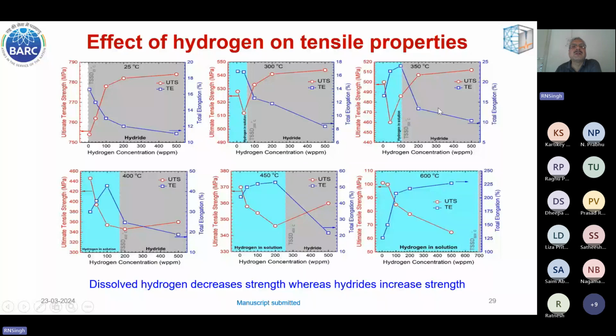You can see that when hydrogen is present in solution, the ultimate tensile strength has reduced. But when hydrogen is present as hydride, there is a marginal increase in ultimate tensile strength. And this is consistent even at 400 degrees Celsius. You see UTS is decreasing with dissolved hydrogen concentration. However, when hydride is present, there is a marginal increase. Same at 450, same at 600 degrees Celsius. If you see total elongation, it shows the reverse behavior. Of course, hydride causes embrittlement, so ductility is reduced.